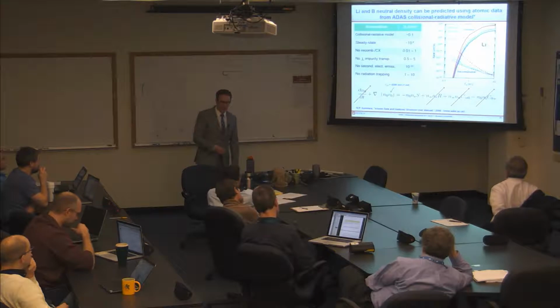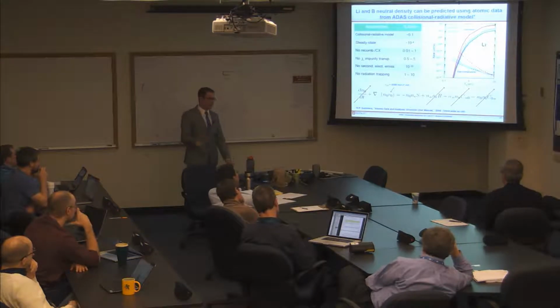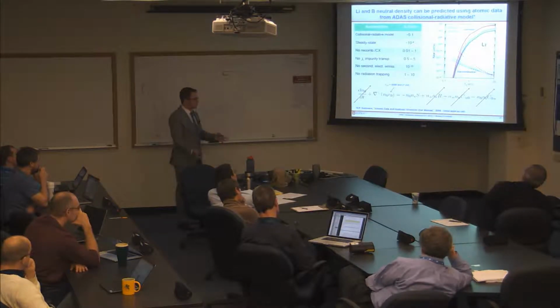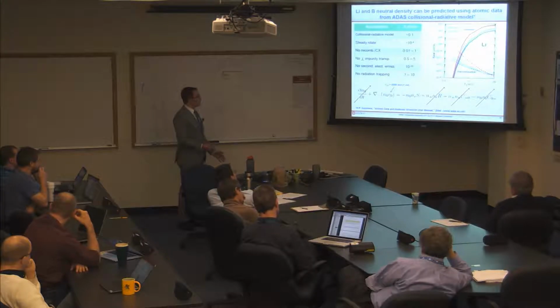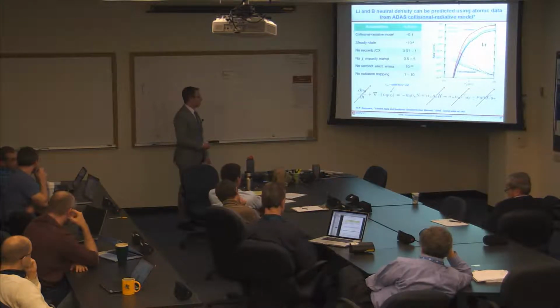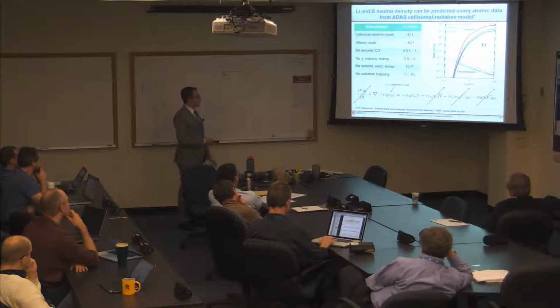Okay, so how do you measure the lithium erosion rate? Well, first off, you need to take your measurements of the lithium radiation, and then you figure out the lithium density. And so the way you do that is you solve the continuity equation for neutral lithium, and you end up being able to drop a lot of these terms because they are small relative to other terms. So S, R, and C are the rate coefficients for the processes of ionization, recombination, and charge exchange.